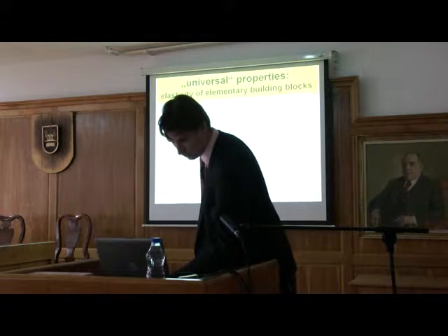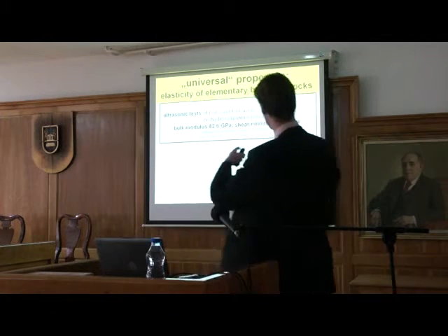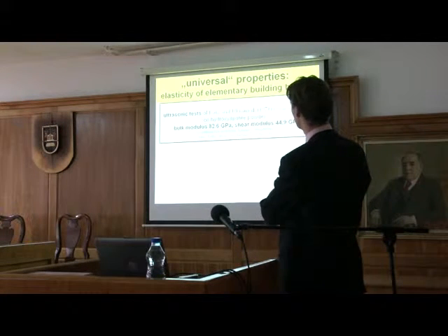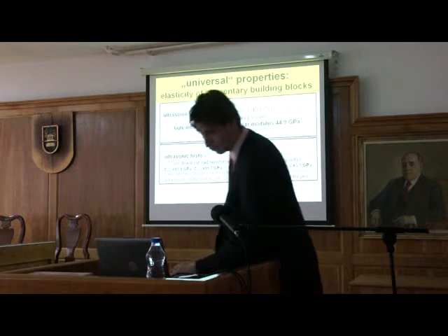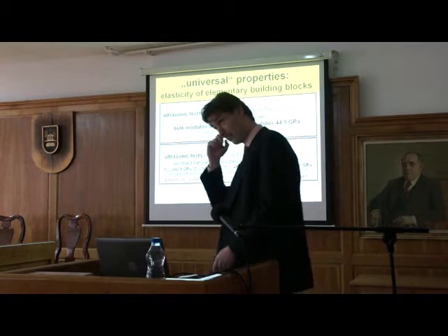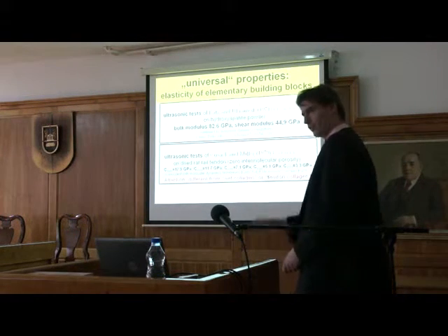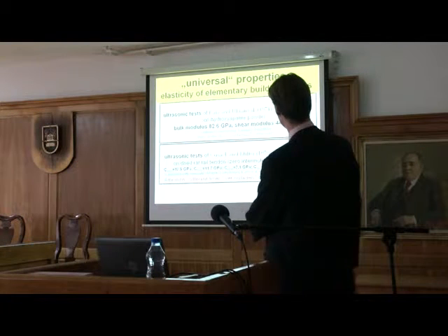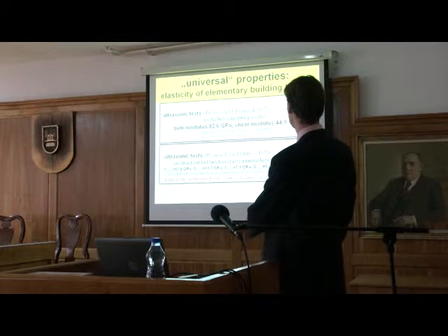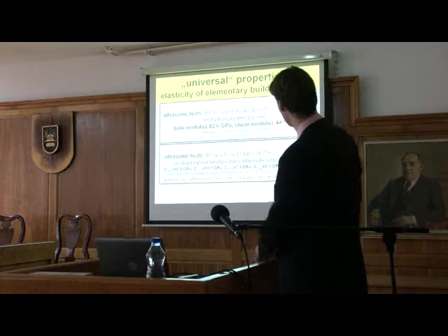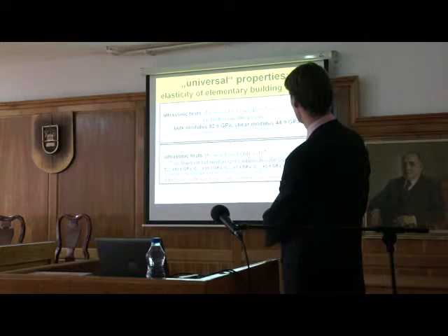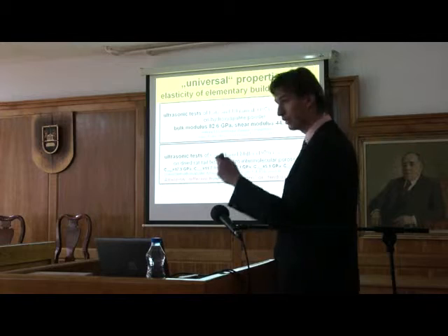Right? And to give a glimpse on this, back to these universal properties, hydroxyapatite from ultrasonic tests. It is confirmed meanwhile by molecular dynamics, so this is cast in stone. Molecular collagen, we have to be careful. We are introducing molecular collagen as the elementary building block, not collagen with water and so on. It's just the molecules. So you have to take something where you have no water and just the molecules. If you take, for example, dry tail tendon, which is the one you can find in literature, you get relatively high Young's moduli, and they are consistent with molecular dynamic simulations and so on. But this is what molecular collagen is about.